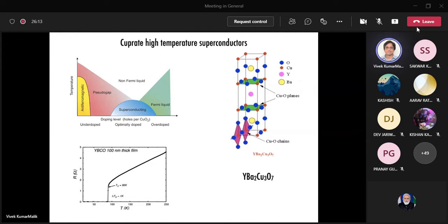So these planes are extended in X. Let's say if we assume this to be the XY plane, then within the XY plane they have these copper oxide planes, CuO2 planes actually. And then along the Z-axis they have these chains, because one of two oxygen atoms is missing within that plane, so they form a chain. These copper oxide chains are actually used to dope the copper oxide planes. As you increase the number of oxygens along the Z-axis, they start to take electrons from the copper oxide planes, and the copper oxide plane becomes doped.